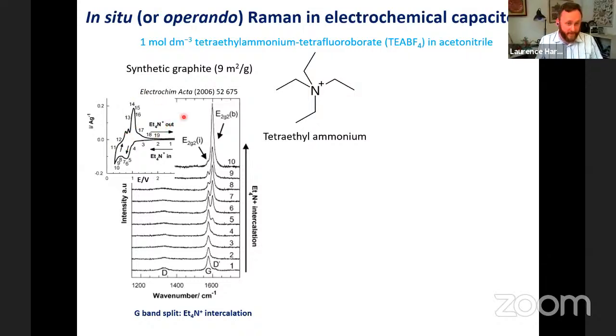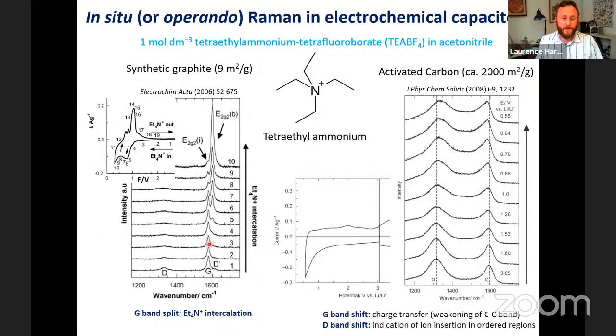Both electrochemically and spectroscopically, you see very clearly there are some very nice redox peaks here, and this results from the tetraethyl ammonium that's been used in our electrolyte inserting in between the graphite layers. And so we see classical splitting of the peaks, which is a result of the species being inserted between the graphite sheets. If we alternatively look at an activated carbon, so this is a carbon that you'd use in a supercapacitor, it has very high surface area.